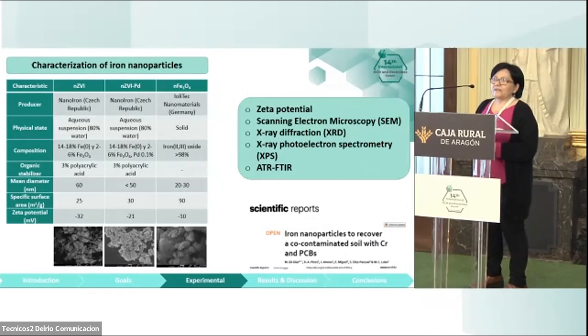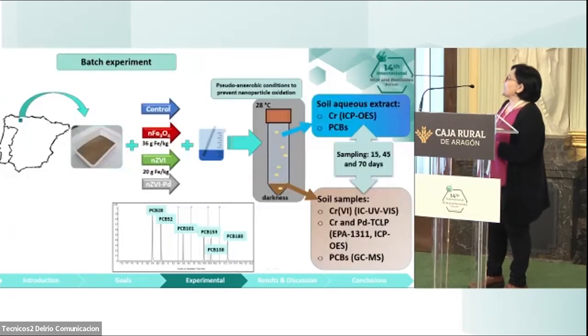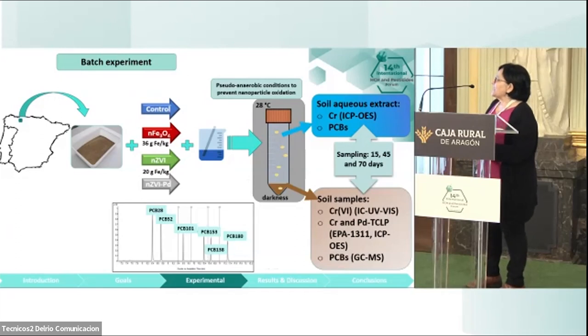Here we can see the characterization of the iron nanoparticles with different techniques in order to prove their reactivity, stabilization, and size. As we can see here, the zero valent iron nanoparticles, both alone or together with Pd, and the nanomagnetite were used in a solid medium. The test was carried out in the lab, and we tried the three nanoparticle types in pseudo-anaerobic conditions. This was to avoid the rapid oxidation of the iron nanoparticles. Once we had controlled temperature conditions, we took different samples at 15, 45, and 70 days.